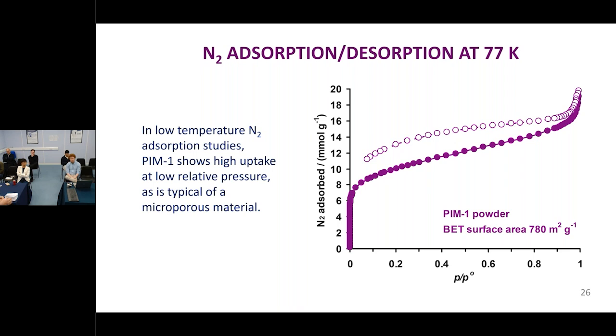Because if you have nitrogen, it doesn't interact very strongly with the surface. It's only relatively weak intermolecular forces. But if you put it in a little space where there's surface all around it, the interactions that there are get magnified. And that's why we're interested in these microporous materials. Even relatively weak interactions are magnified. You get much stronger sorption in the micropore than you would on a flat surface. And so that's very typical of things like zeolites and carbons, activated carbons.